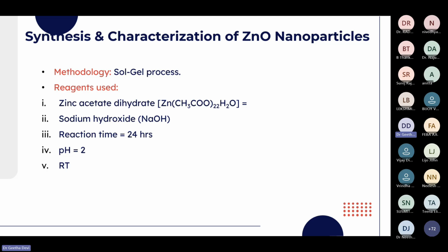Next, we have synthesized the zinc oxide nanoparticle by the sol-gel method. We used zinc acetate dihydrate and sodium hydroxide, and the reaction time was maintained at 24 hours at a pH of 2.